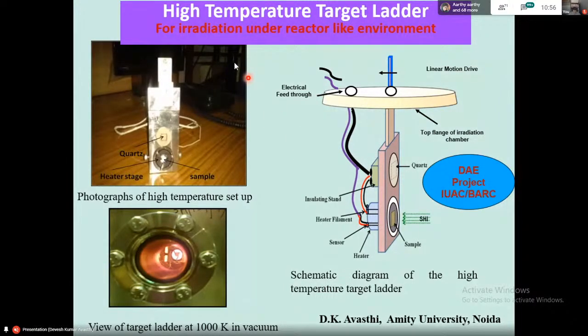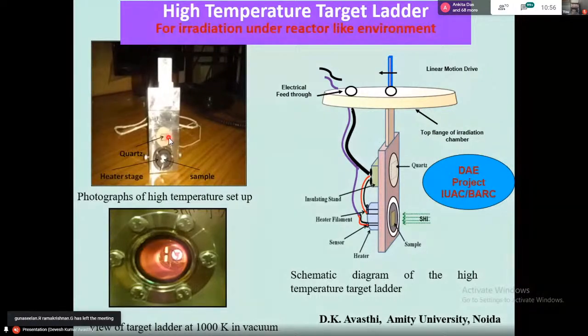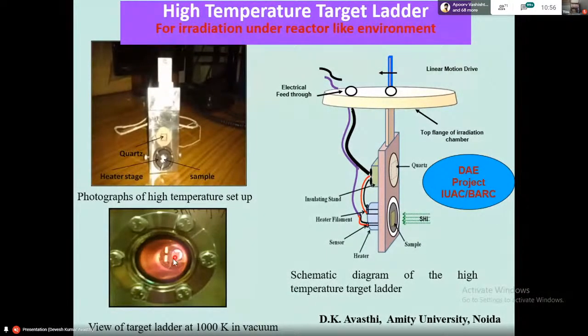It is a setup for making irradiation under reactor-like conditions. That means the temperature should be 1000 degrees centigrade or so, and at that temperature, you irradiate the material. So this is a heating stage, and this is the part for the beam, and this is the actual setup, and this is a flange through which you can see inside. When it is heated, it is red hot, and in this condition the ion beam is bombarded here like this. This is a schematic. And then we study that material under reactor-like conditions.